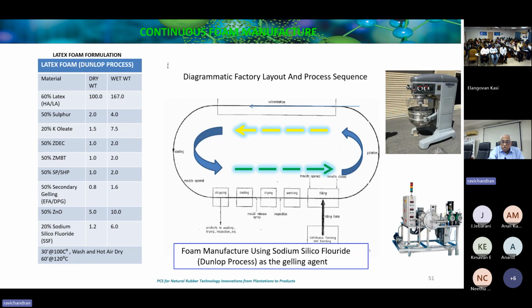Here I've just shown you the production sequence for foam manufacturing. For manufacture, there are two basic processes. One is called the Dunlop process. The other is called the Talalay process. This is the Dunlop process. So you see on the right-hand side, that's the machine for making it in a batch way. That means we form the latex in a batch and we pour it into the mold, and it then goes through the whole cycle of vulcanization and stripping, cooling, drying, washing. Or we can do continuous feeding, so that as the molds are coming, it's continuously fed. That's where we have high volume production. We use the continuous feeding machine.